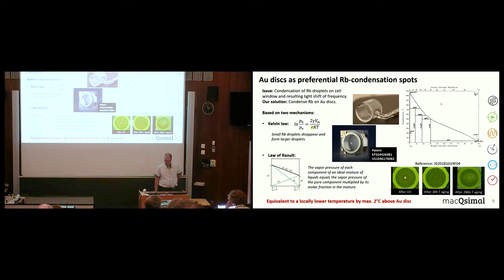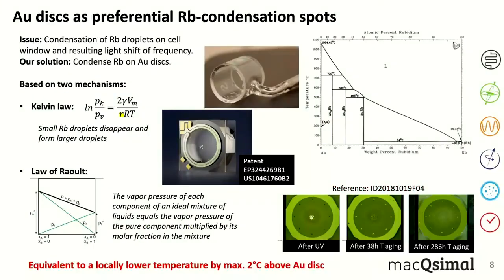So one issue in general with atomic vapor cells is that the rubidium has a tendency to condense on the glass window here, and if you shine then a laser through to probe the atoms, you get a light shift of the frequency, and this has a very high impact on the stability of the clock. Now in bigger glass-blown vapor cells, as we see it here, often this problem can be solved because the cells are quite large.